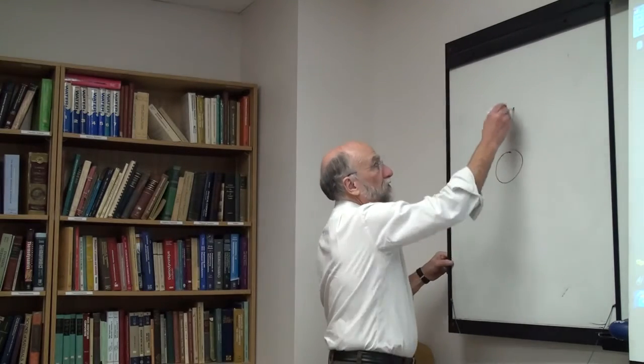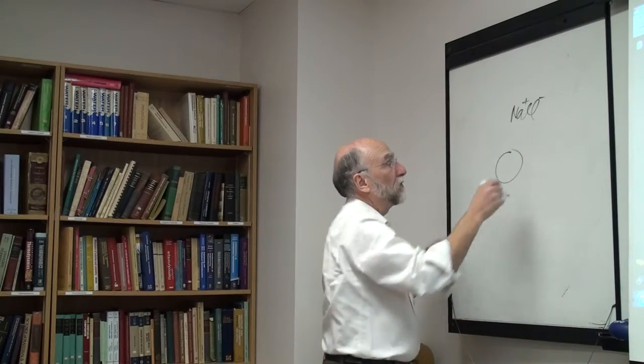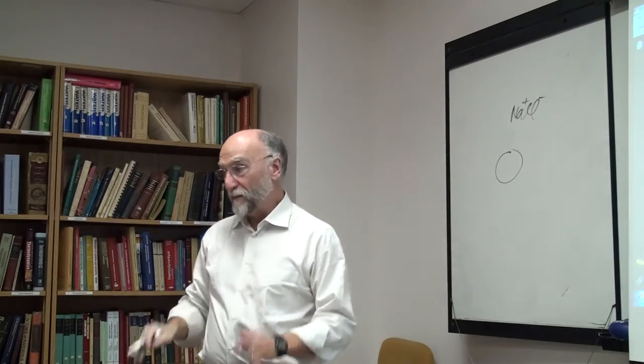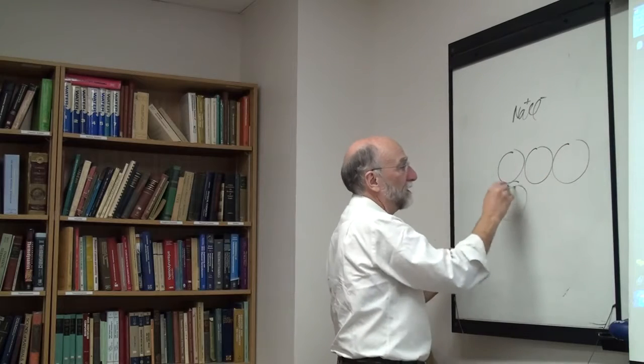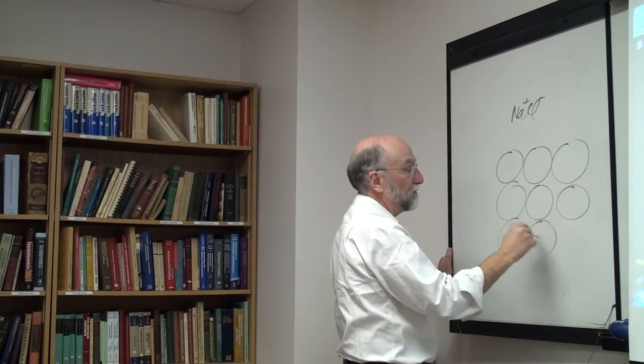Because remember, in all the models we've been talking about, the quasi-chemical model and the regular solution model, the parameters are only dealing with first nearest neighbor, second nearest neighbor forces. We're not talking about long range forces. So if a system has locally virtually 2 sublattices, for all intents and purposes, it's easier to treat it that way. So let's say we take sodium chloride, liquid. Sodium chloride solid, no question, it has 2 sublattices, a cation lattice and an anion lattice. Sodium chloride solid is fine. Sodium chloride liquid, however, to all intents and purposes, can be treated by the same model.